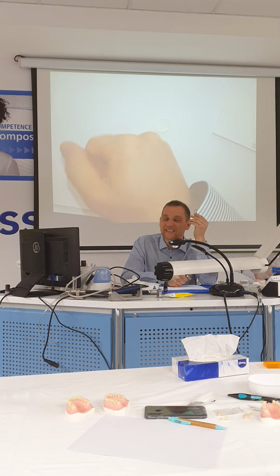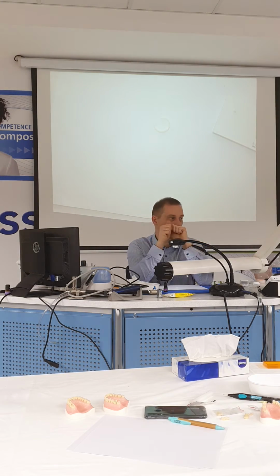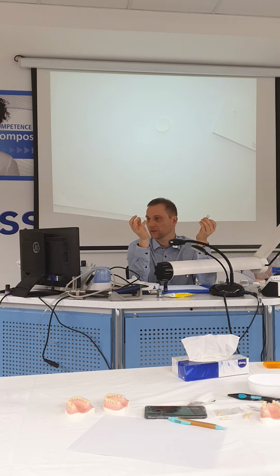And Multilink Speed has no bonding to this plastic. It is just micromechanical retention here. That's why it is so important for these materials to have a retentive preparation design. Because you'll get very good retention already due to the design, due to the shape of your restoration. Here we can rotate the normal crown, you can never rotate it. It will stay there without any problems. But the crown itself should be strong enough, like zirconia, lithium disilicate or metal based. And of course, with zirconia and metals, you get even higher bonding strength because you'll also get chemical bonding in addition to the micromechanical.